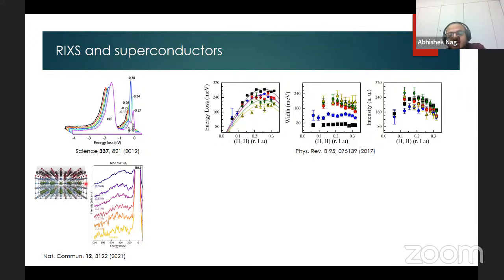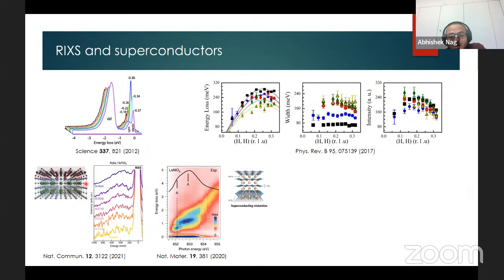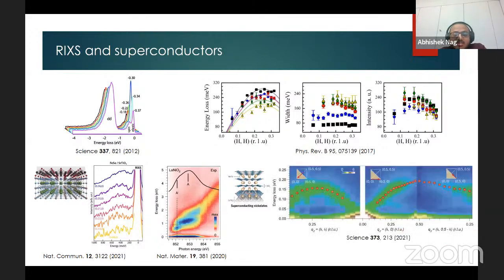So it's quite obvious that the recently discovered nickelate superconducting thin films that Professor Tanusri Saha-Dasgupta described in her talk this morning would also be studied using RIXS. Using nickel L-edge RIXS, a clear evidence of hybridization with the rare earth element was observed in these superconductors, which is absent in cuprates. And although the magnetic ordering in these nickelates is still under debate, this year we observed that significantly strong magnetic excitations are present in the parent and the superconducting nickelates.